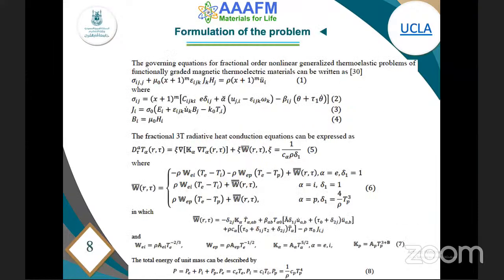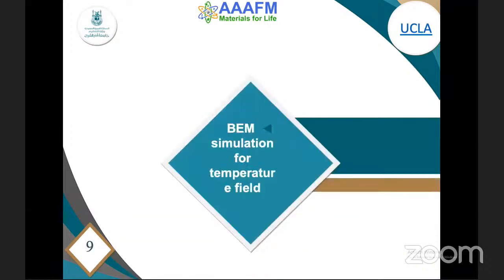Formulation of the problem. The governing equations for fractional order nonlinear generalized thermoelastic problems of functionally graded magnetic thermoelectric materials can be written as equation 1, equation 2, 3, and 4. The fractional three-temperature radiative heat conduction equations can be expressed as equation 5 with equation 6 and 7. The total energy of the unit mass can be described as in equation 8. Boundary element method simulation for temperature.